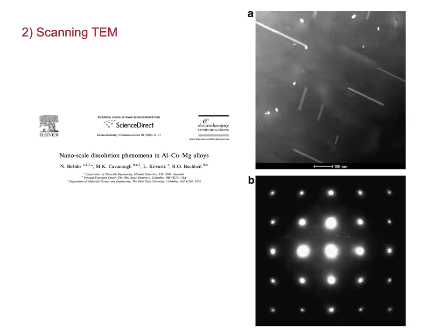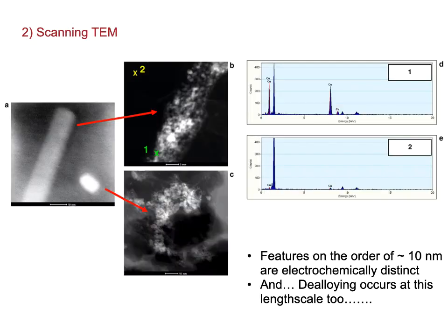Alright, so look, scanning TEM also allowed, in a digitized manner, for images to be obtained at very high magnification and with compositional contrast. Here we see an example of a model aluminium-copper-magnesium alloy with S-phase precipitates.